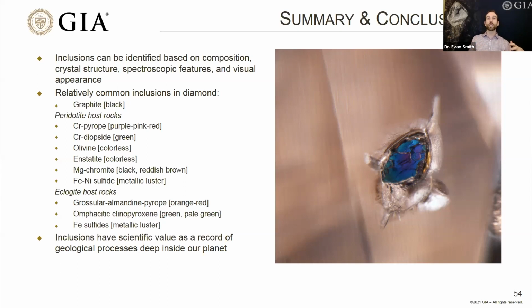The drawback of looking at diamonds in the rough is that the surface of the diamond is very irregular, and sometimes it can even be frosted. So it's very difficult to see the inclusions in it. And if you wanted to examine them, for instance, under the microscope or use Raman spectroscopy, if you can't see the inclusions, you really can't study them very effectively. So then you're limited to more expensive or time-consuming techniques like X-ray diffraction, and you would be doing it blind, trying to bounce an X-ray beam into this diamond and examine whatever inclusions are present.